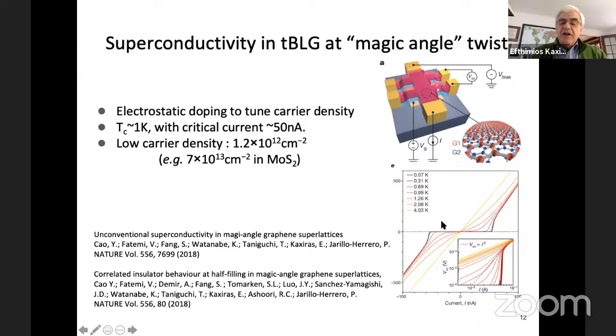And they measured the resistance as a function of the current. So here is the resistance as a function of the current at different temperatures. The different curves here correspond to different temperatures. And as you lower the temperature, yellow is 4 degrees Kelvin, the black is less than 1 degree Kelvin, you see that the resistance basically goes to zero. And when you have zero resistance, you have superconductivity. So this twisted bilayer graphene shows the characteristic behavior of a superconductor at this very special angle. It was at about 1 degree.